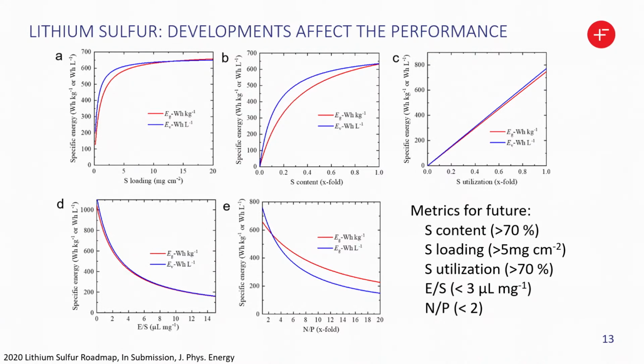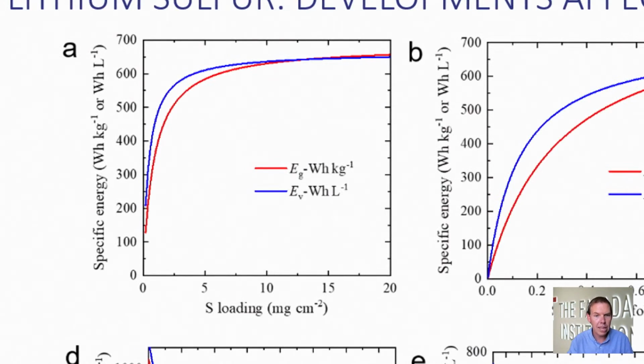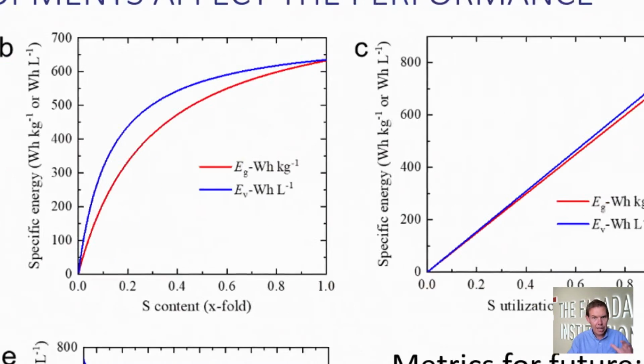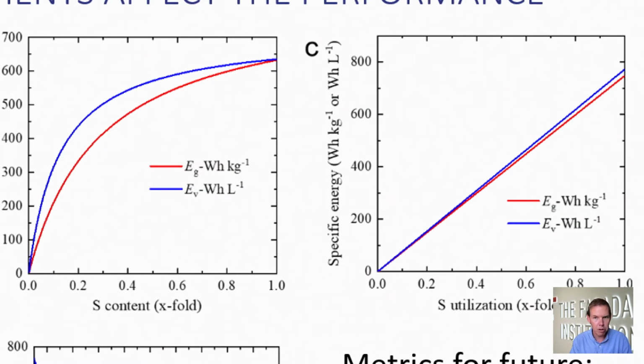The goal to try and improve the specific energy, both per unit volume and per unit mass, has a number of underpinning requirements in order to achieve the targets of 500 watt-hours per kilogram and above. We can see that those fundamental targets can then be translated to materials performance criteria, which includes engineering cells which have enough sulfur in them, making sure that we utilize that sulfur effectively, minimizing the ratio between the amount of solid material and the amount of liquid material that we have within the cell, and also making sure that we're properly balancing the negative and the positive electrode materials.